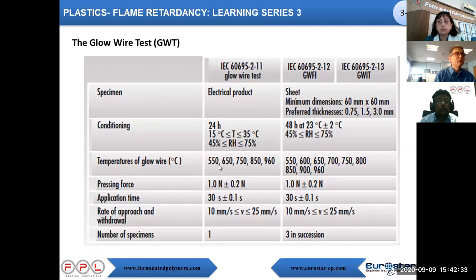Temperature of the glow wire. For the glow wire test, there are very precise temperatures from 550 to 960. You may ask why those temperatures. I think 960 is self-explaining because it's very difficult to calibrate those wires, and 960 is the exact temperature of melting of silver. When you calibrate the glow wire test, you put a tiny piece of silver foil on the wire, and you see when it melts. And 960 being a sharp melting point for silver, it helps to calibrate the wire. So it has been the standard for many years, but of course it's very stringent. And now there are temperatures in between for different applications.